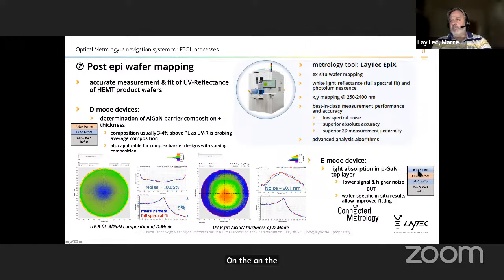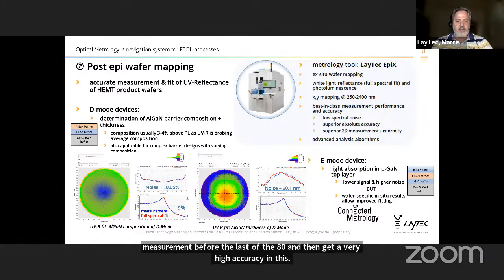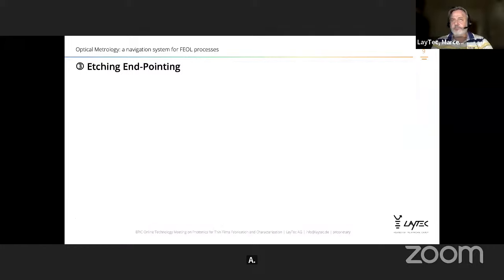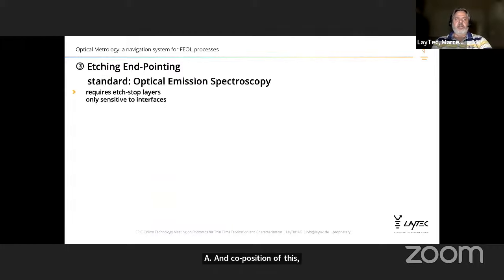Here there is the problem that the pGaN on top is absorbing some light, and so it's reducing the measurement capability of photoluminescence, for example. That's why it cannot be used in this case. But since we know from the EPI how the wafer is structured, then we can join together this measurement before and after the EPI, and then get to a very high accuracy in determination of thickness and composition of this crucial layer. And last but not least, the etching and endpoint, as I was mentioning earlier.